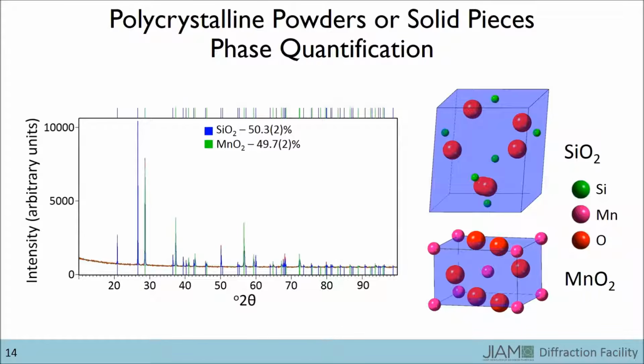The blue lines in the diffraction pattern designate the silicon oxide peaks, while the green lines designate the manganese oxide peaks. The software available in the diffraction facility greatly helps in the determination of which peaks belong to which phase. If the sample is prepared and tested appropriately, you may also be able to determine how much of each phase is in your material. When making the sample, I had weighed 50.4% silicon oxide and 49.6% manganese oxide. As you can see, the analysis is very close.